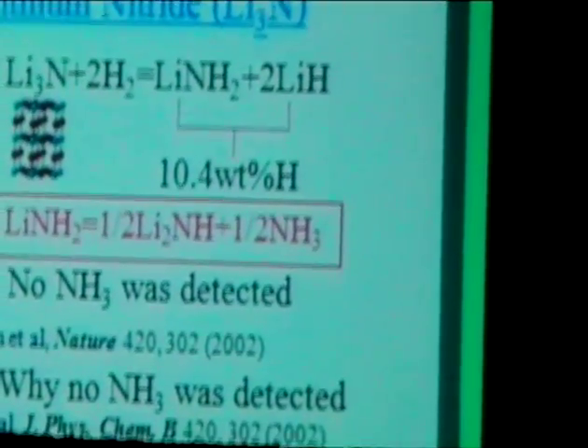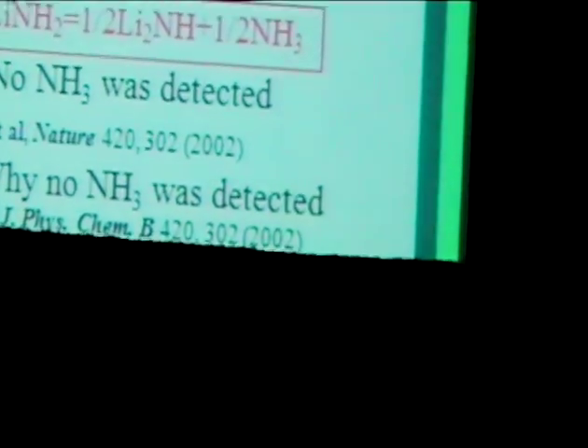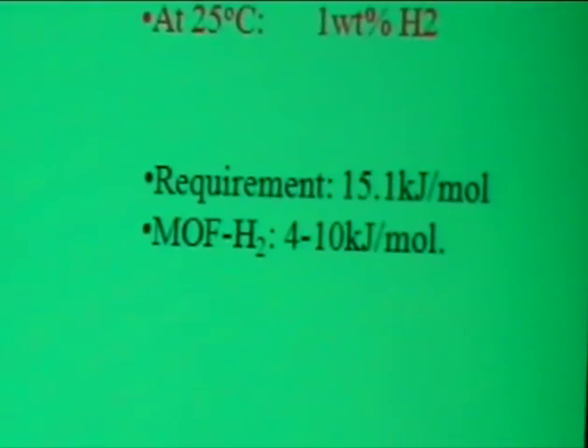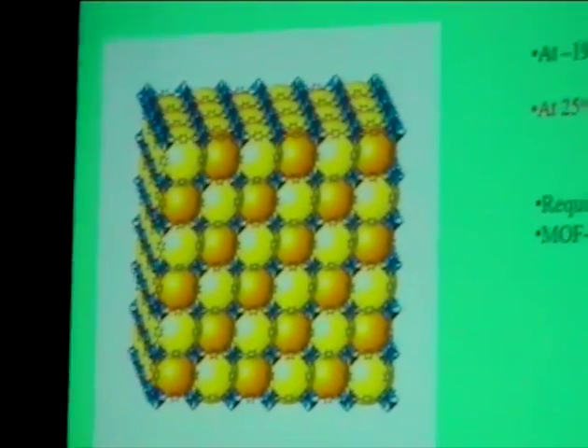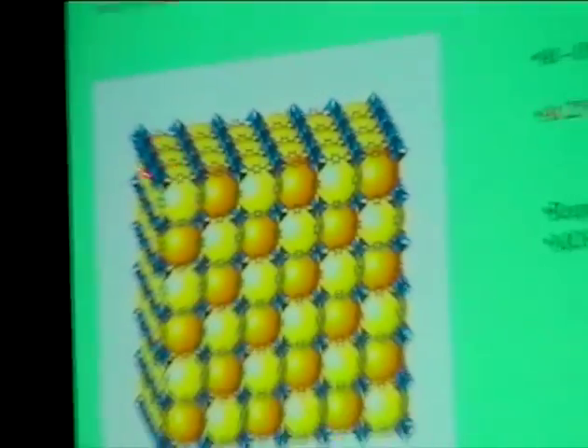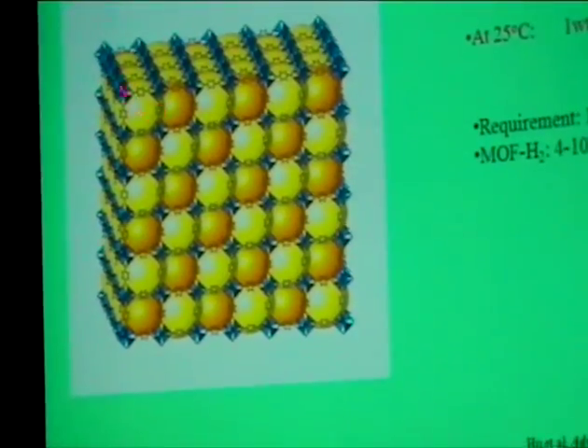So after 2003, many groups did research in this area. So these are the two new materials. And then the third one is the metal organic framework. That paper was the first paper published about hydrogen storage. The model is from Yaghi's group. They published a paper in 2003 in Science. They reported that a metal organic framework can store hydrogen at low temperature. So you can see this material. The metal organic framework is an inorganic cluster linked by organic rings, so they form the framework.